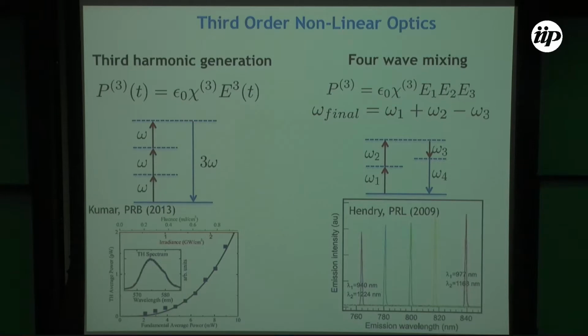Another third order nonlinear optics experiment is called 4-wave mixing. It's very similar to the third harmonic, but now we consider that we have 3 different electric fields, each with a different energy, omega 1, omega 2, and omega 3. If you put these 3 fields on your material, it's going to generate a 4th field. The frequency of this 4th field can be a different combination of these 3 incoming energies. It can be omega 1 plus omega 2 minus omega 3, or omega 1 minus omega 2 plus omega 3, and so on. We have a lot of different combinations, but here we just consider this one.